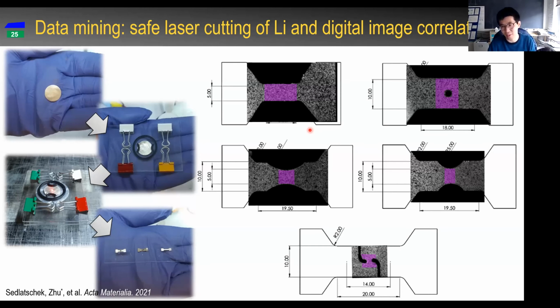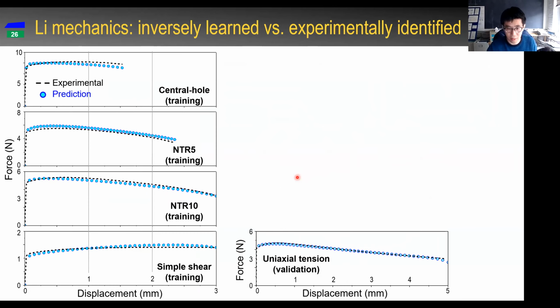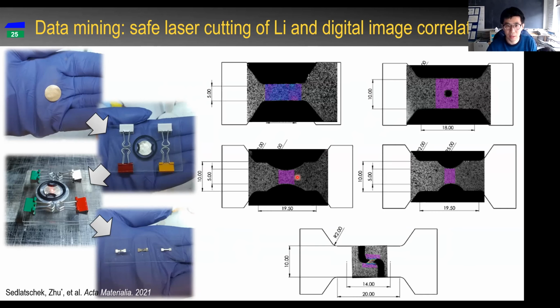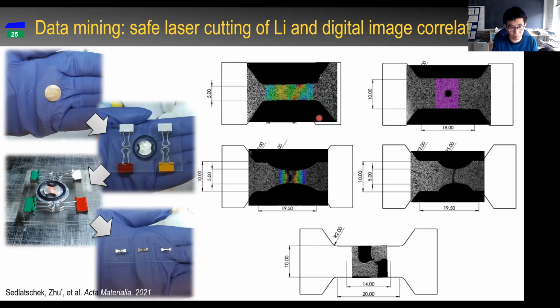And here are the test results. We designed 5 different loading conditions, and all these tests are performed under a camera so that we can capture the strain field. Is it playing? Oh, sorry. Okay, yeah, we can see there is a strain localization in each test, and we see the fracture clearly, with the help of the DIC system.